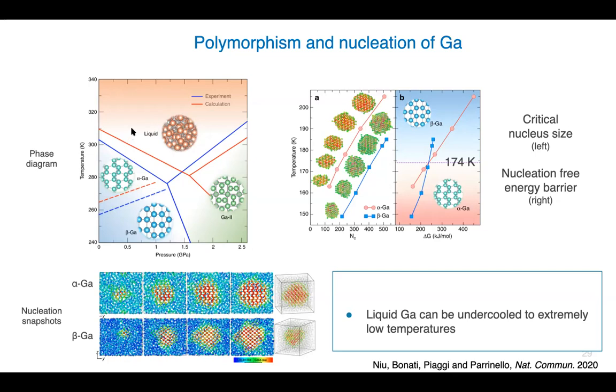So gallium can be undercooled extremely, and up to a certain temperature, it undercools in the beta phase rather than the alpha phase. And above that, the system crystallizes when undercooled into the alpha phase. And we studied this process. We don't have much time to go into the details, but you can see here the barrier for going from one phase to the other.